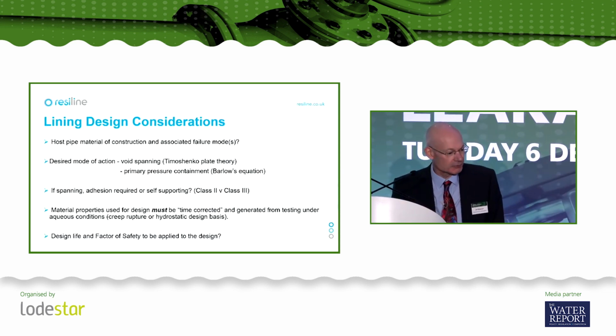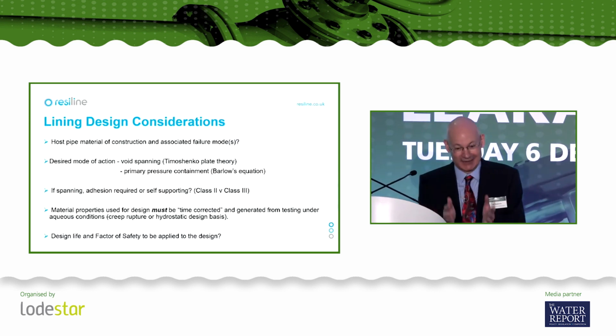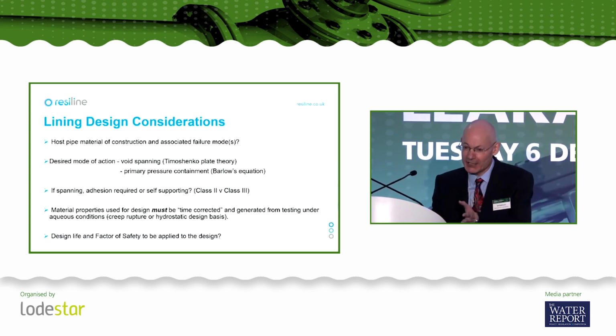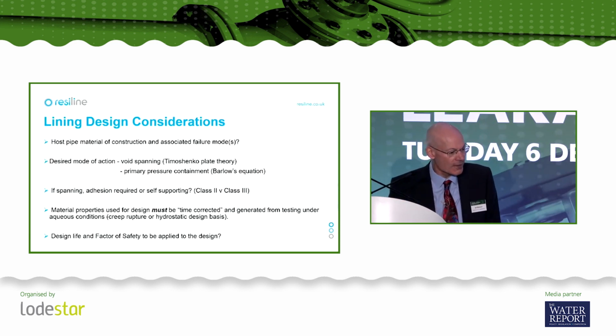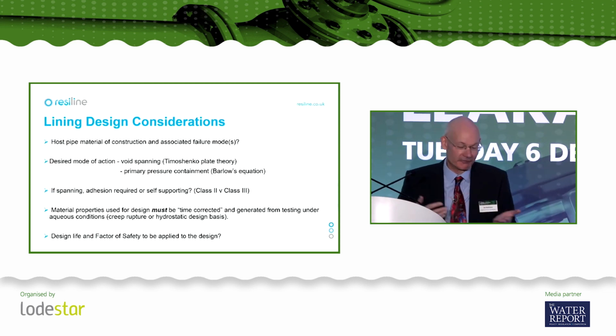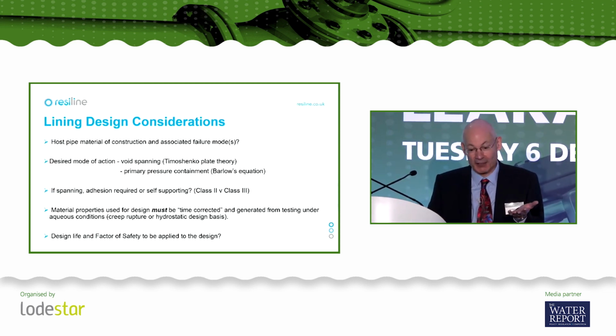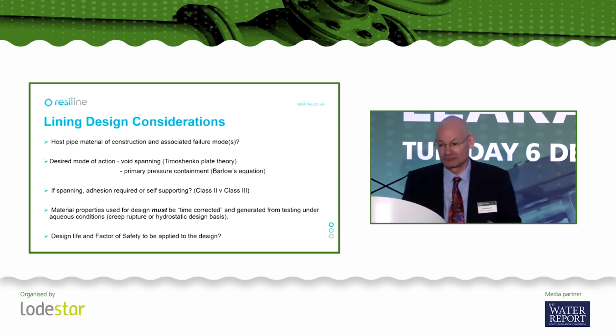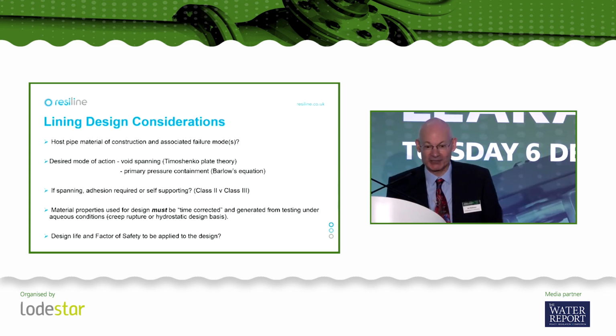So if we move on to some design considerations for the liner. Now, when I say design, I mean the actual installation of a liner. So if there's a scheme that's a candidate for lining, how do we design the lining in terms of thickness? So some pertinent questions. Fairly obviously, what's the main constructed from? Different materials of construction fail in different ways. For example, small diameter cast iron mains generally fail quite differently to ductile iron or PVC mains or even asbestos cement mains.